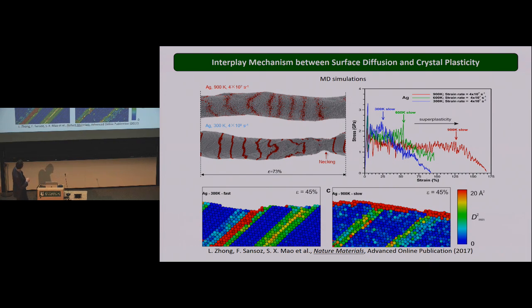When we reduce the temperature, of course, we prevent surface diffusion. In this case, we see a lot more slip bands, and these slip bands are the cause of stress concentration that accelerates the necking of the material.